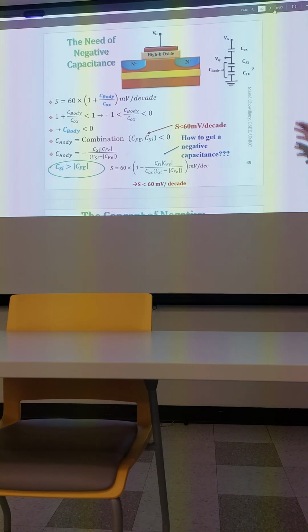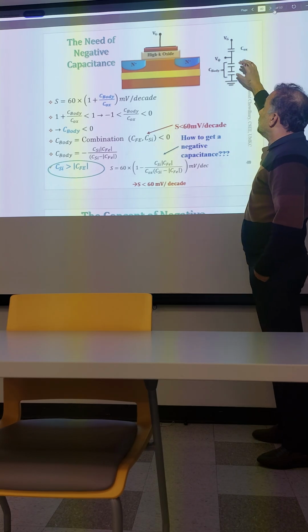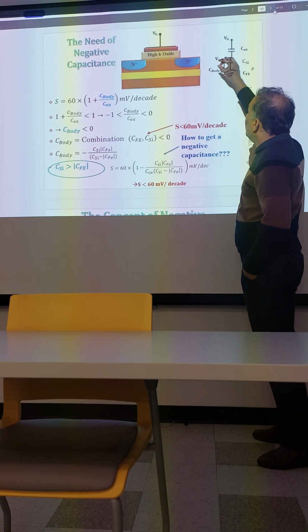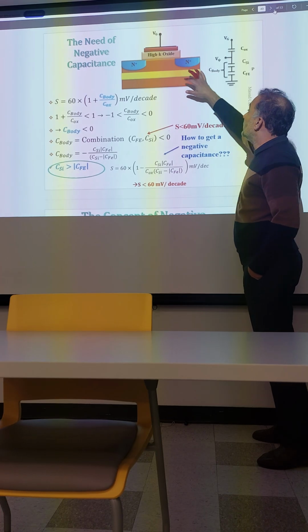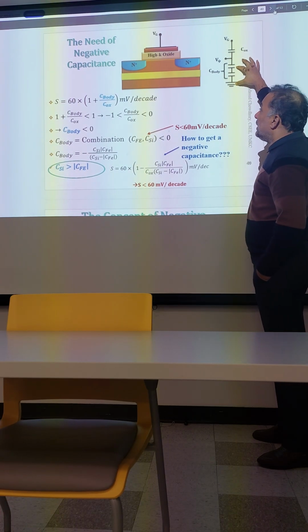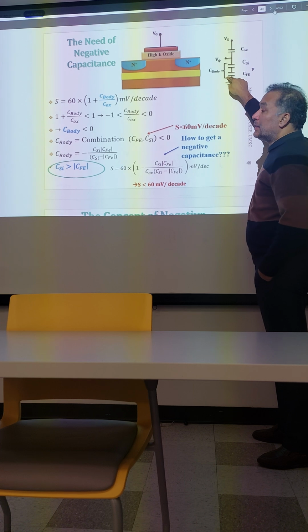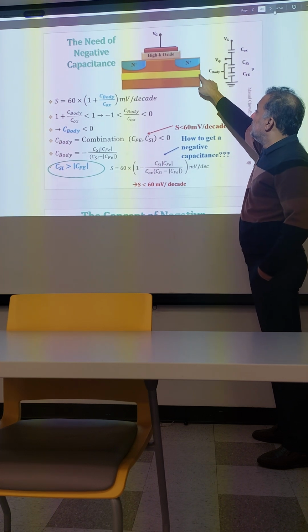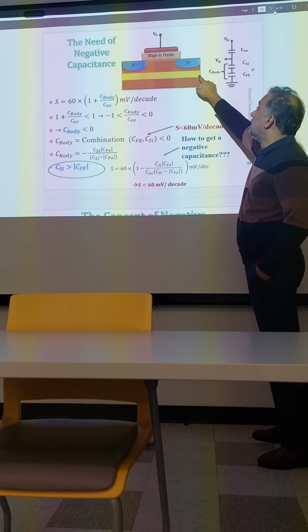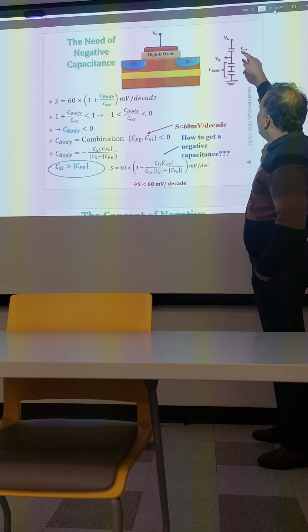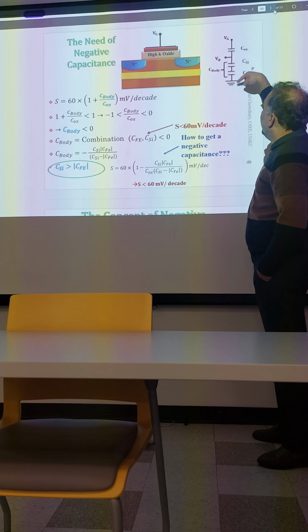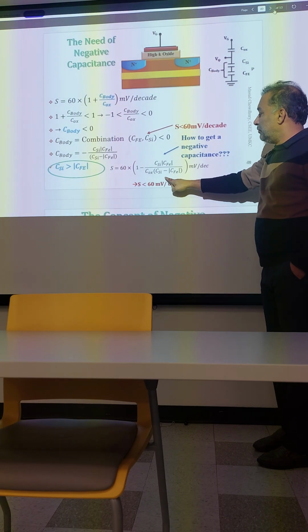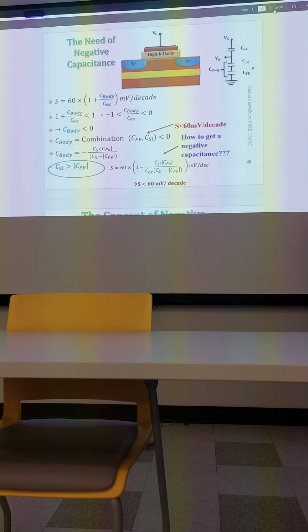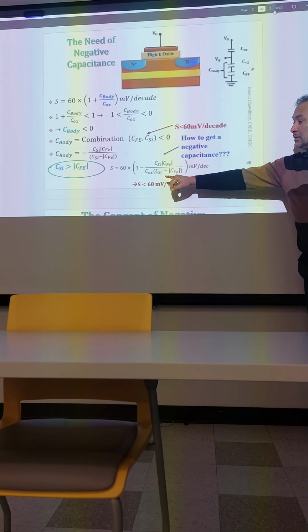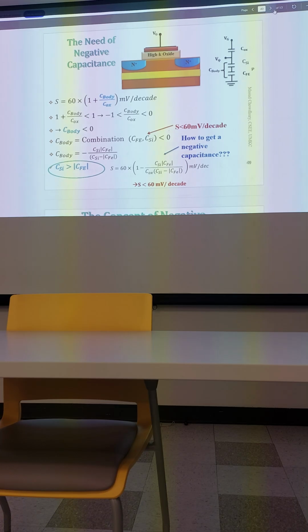So, inside the body, the equivalent circuit will be: you have the oxide capacitance, you will still have a silicon capacitance for this portion, and a capacitance buried inside the body due to the ferroelectric capacitance embedded for this ferroelectric insulation layer. So, if we can control the relative values of these three capacitances, we can control the value of this fraction, and thereby we can control the value of subthreshold swing, how far below 60 millivolt per decade it can go.